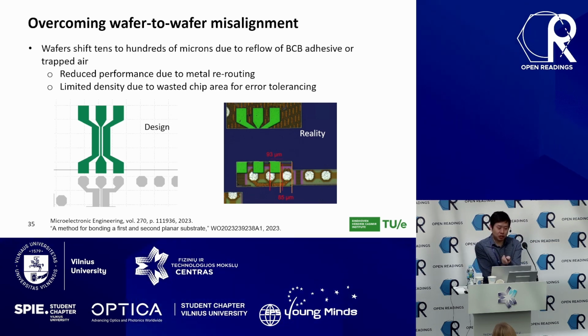And our measurement shows that it can drift up to hundreds of micrometers, which is horrible because a laser is 2 micrometer in width, right? Electrical pad may be 100 micrometer. So if you drift that much, you misalign your laser and your IC driver completely. And this is an example. So from the design, we align the electrodes so perfectly. But in reality, as you can see, there's a significant drift between the two wafers.